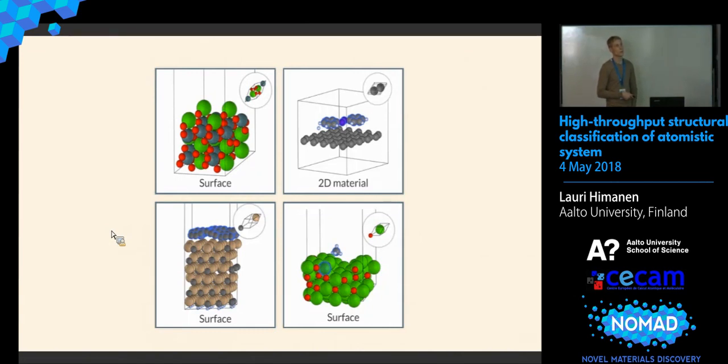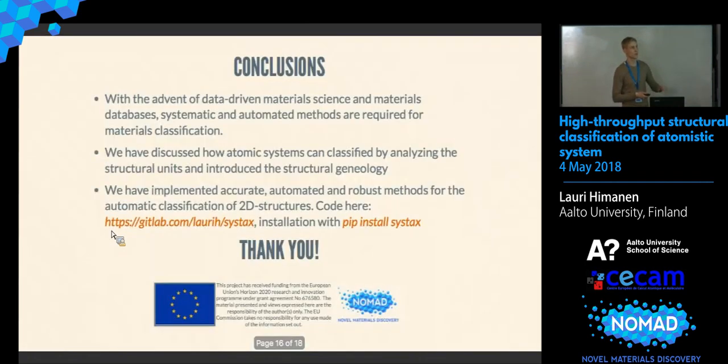We correctly identify a bit more complex surfaces which have different sorts of coatings, terminations. Once again, finding the correct unit cell, and identifying that there are two different terminations on the two sides of the surface. And we can also work with kinked or stepped surfaces. So this is an example where we have an uneven surface. We actually have what could be classified as a substitution, one atom substituted on the surface, and then an adsorbate molecule on top of the surface.